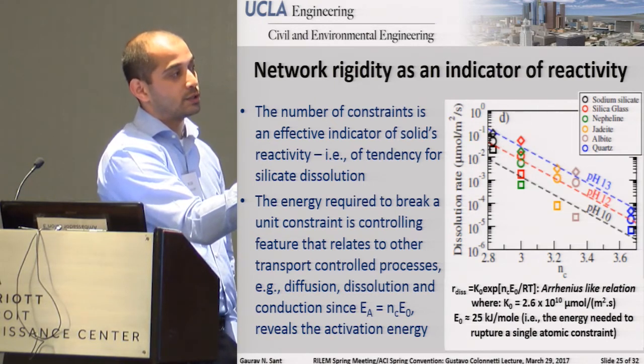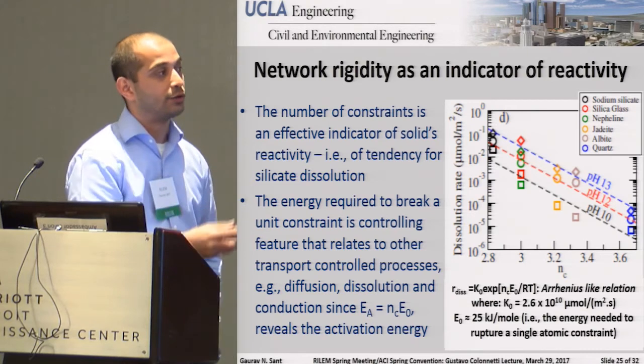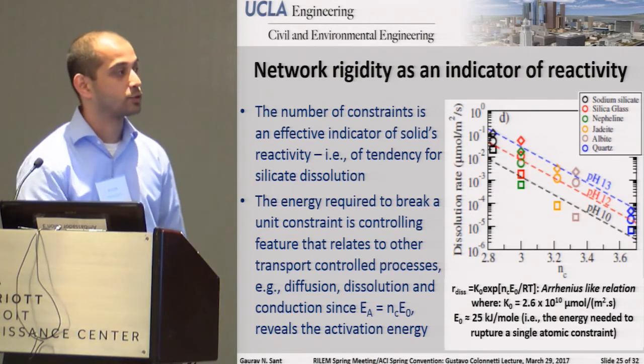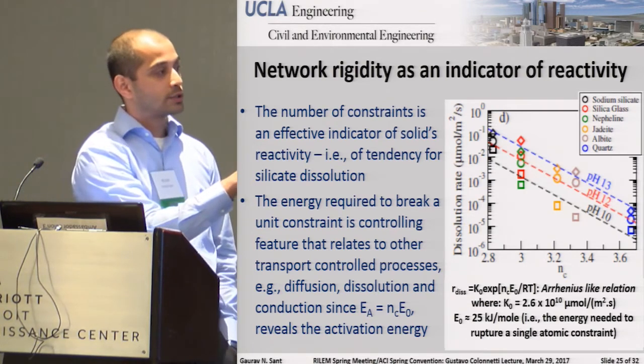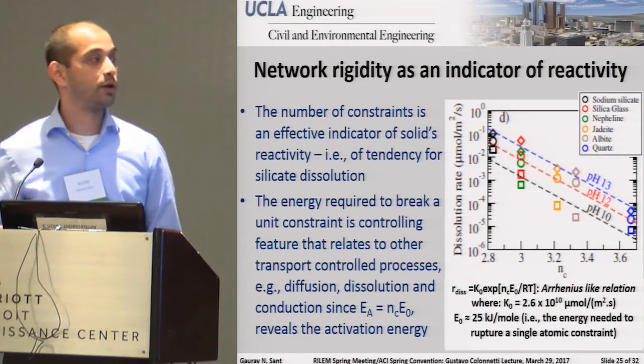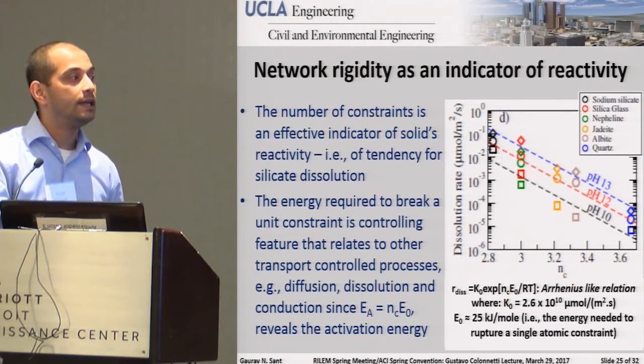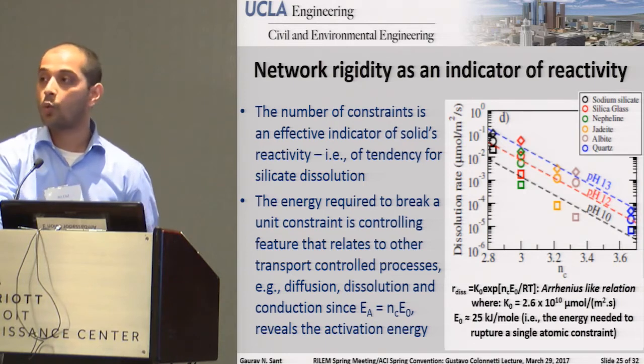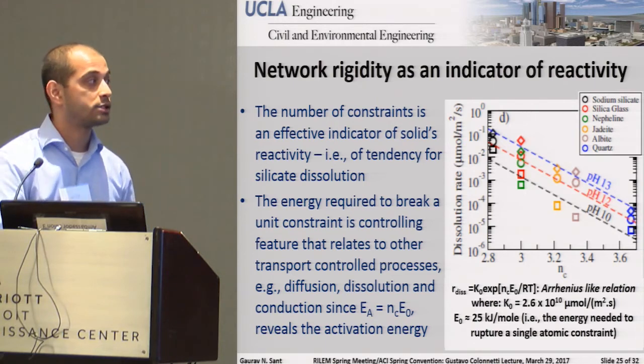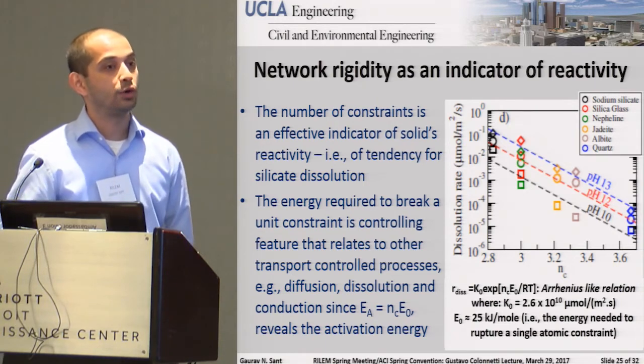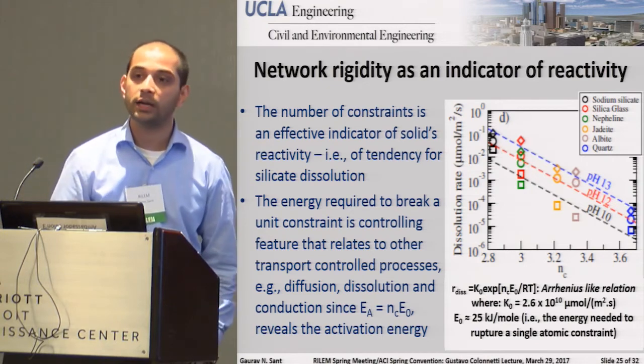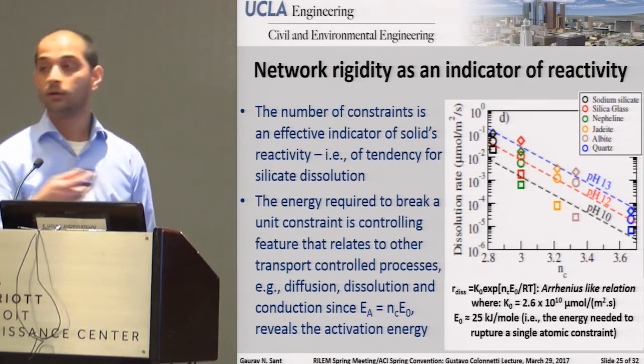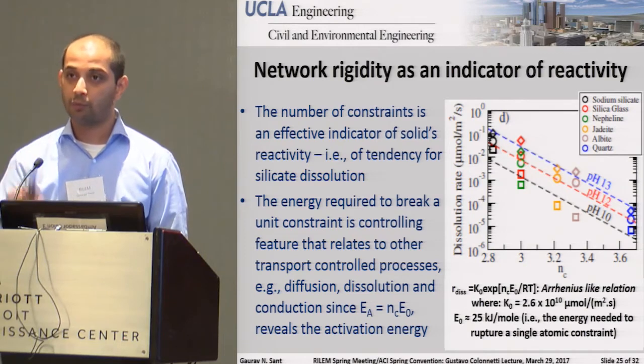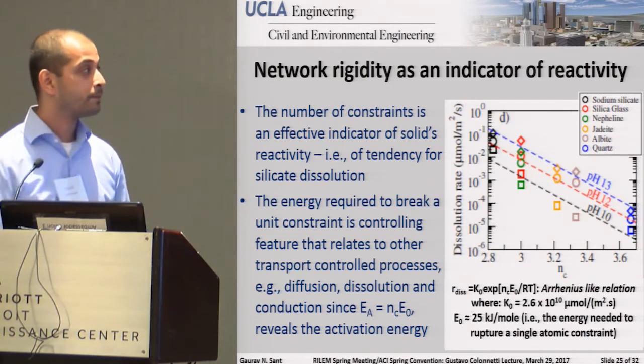You know what the number of constraints is. K-naught is basically just your intrinsic rate constant. It's your pre-exponential factor. That's what you want to call it. But the nice thing is you can start to tell E-naught takes a value of about 25 kilojoules per mole. So what this really is, it's telling you the energy that's required to rupture a unit constraint. Now, this is actually quite important because you're now starting to be able to lend some quantitative energy numbers that are associated with taking a solid and transferring it from within itself into the solution.